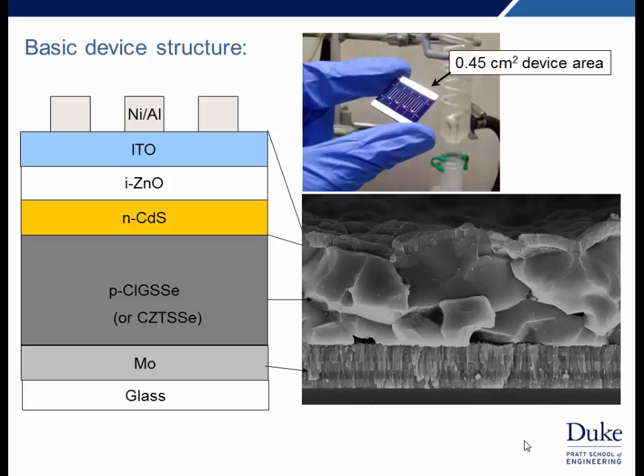We use a glass substrate on which is deposited, generally by sputtering, molybdenum as a back contact. Then we have our absorber, which is either the CIGS or the CZTS. And on top of that, chemical bath deposited cadmium sulfide is the N-type material. This could also be indium sulfide, zinc oxysulfide, etc. And then finally, we have our transparent top contact.